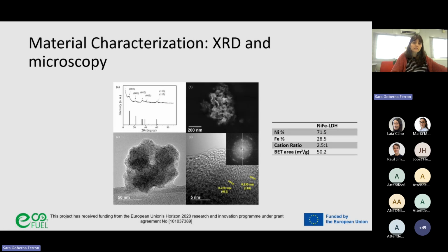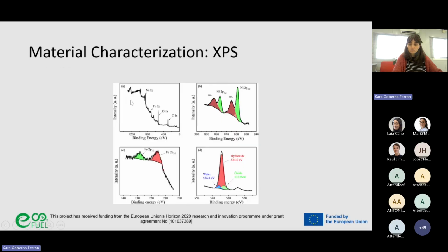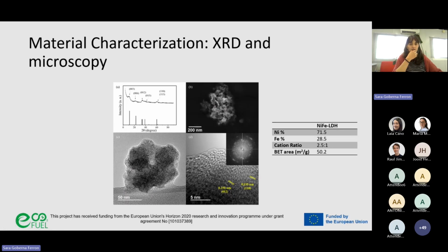For example, here you can see some characterization by X-ray diffraction and by microscopy. Basically, in the X-ray diffraction pattern, we see the characteristic features corresponding to nickel-based LDH structure. One important point is that the peaks are very broad, and this is already indicating some degree of low crystallinity. This is due to the solvent-free synthetic method.